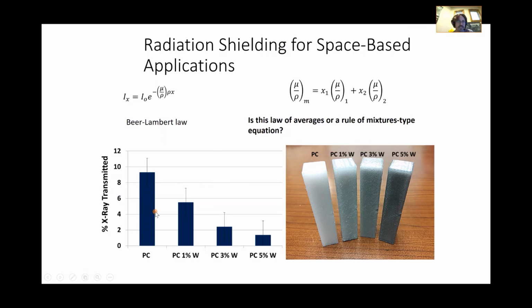So if you're in a pinch and you have a lot of polycarbonate and want to shield yourself from X-rays, it'll actually do a pretty good job. Adding 1% by weight tungsten decreased transmission pretty significantly, then 3% and 5%. With the error bar, we're at about 3% transmitted X-rays. We made a composite not for strength, but for X-ray shielding, and these were the results.